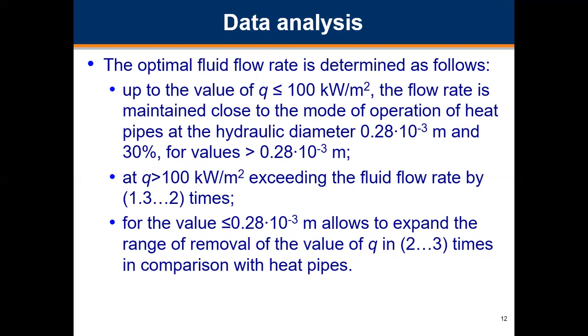Q greater than 100 kilowatt per square meter, exceeding the flow rate by 1.3 to 2 times for the value less than or equal to 0.28 times 10 to the power of negative 3 meters. This allows to expand the range of removal of the value of Q by 2 to 3 times in comparison with heat pipes.